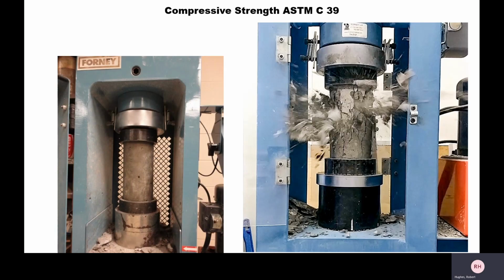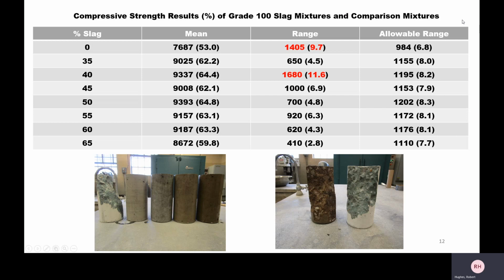So we'll look at our compressive strength results. Now, this is what I was saying, when our 0% and 40% did not meet the allowable range from ASTM C670. But you can see our mean compressive strength, not linearly necessarily, does increase with higher substitutions. And we're not extremely disheartened about the non-linearity because this isn't really the main objective of the research. It is definitely an excellent byproduct of what we're trying to reach. We're trying to get to lower permeability, but an increase in compressive strength is definitely never a bad thing. So, like I said, the 0 and 40 are out of their allowable ranges, but it is an acceptable byproduct from what we're trying to do.